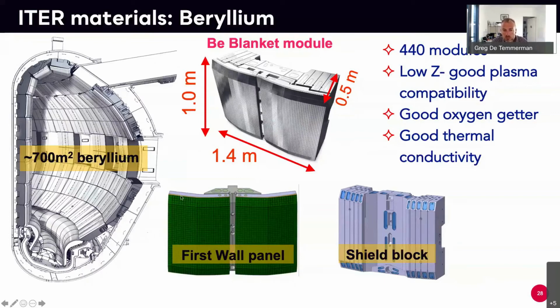And what you also might see is that all those panels are actually segmented. So there are small blocks of beryllium placed next to each other, and that's to accommodate for thermal expansion and to avoid the formation of large cracks, because you have a lot of thermal gradients, so components tend to deform. And in order to make sure that the beryllium armor is holding, you basically segment everything.